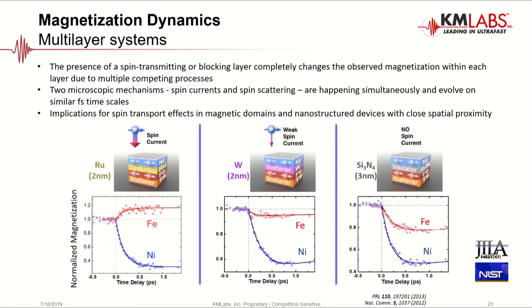And the study that was done here was, again, using the nickel and iron systems, placing them in very close proximity to one another with different separators. So in the far left case, we have a conducting separator. In the middle case, we have a scattering tungsten layer. And on the far right, we have a silicon nitride insulator. And so what we can do here is we can pump some energy into the system and watch how the spin states of nickel and iron evolve over time and try to understand how or if they're interacting with one another.